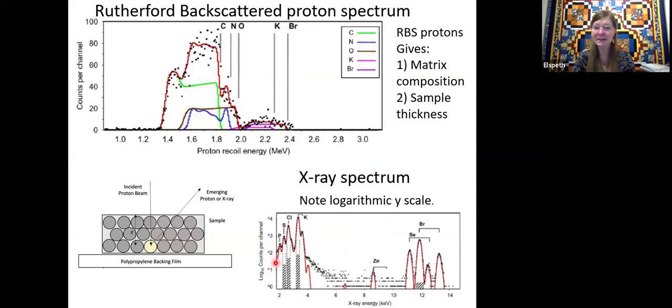We can detect magnesium and sodium, but only if we take the filter off the detector, which might damage it. So we prefer not to do that. But you can see the sulfur peak here, which is due to the methionines and the sulfurs in the protein. And there's the zinc, which this protein actually contained. It was a selenium derivative, and it was in a potassium bromide buffer. So we can see all these peaks here.